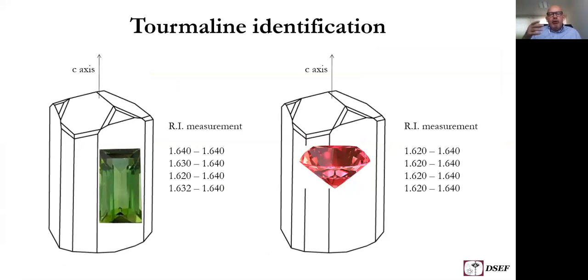Making a few comments on the identification of tourmaline, I just mentioned the pleochroism, which is quite important. When you look at a green tourmaline, like this rectangular faceted stone here, and you put it on the refractometer, and I hope that people are still using refractometers, and you measure it, if the table is oriented exactly parallel to the optic axis, or the crystallographic C-axis, you get a single value. We actually measure the direction of single refraction. Then when you rotate the stone you get the birefringence, and if you rotate the stone so that the table is perpendicular to the optic axis, you get maximum birefringence.